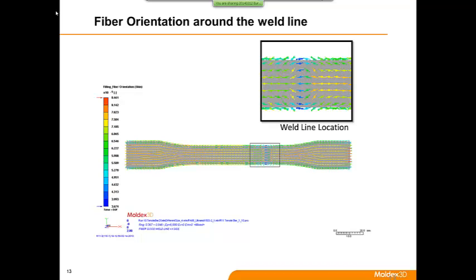You can see this melt front is coming from left and right. There's a weld line in the center. Near that weld line location, the fiber is basically not following the flow direction, but perpendicular to that. So this creates a problem.